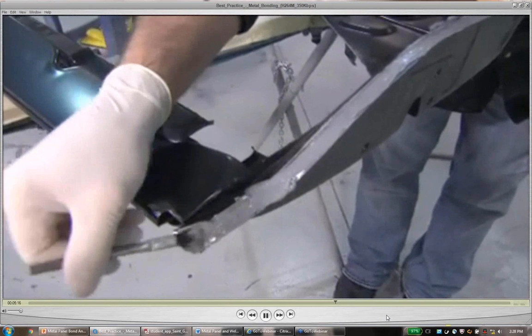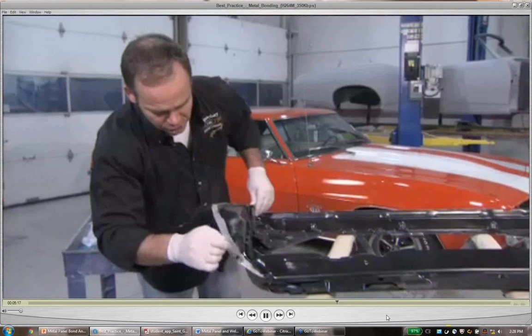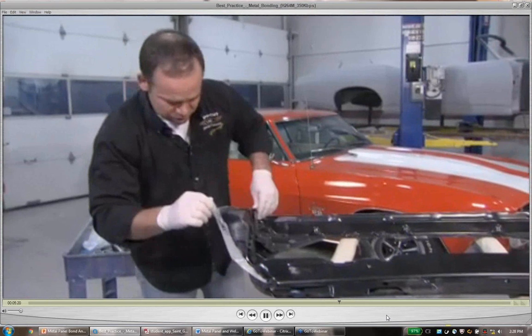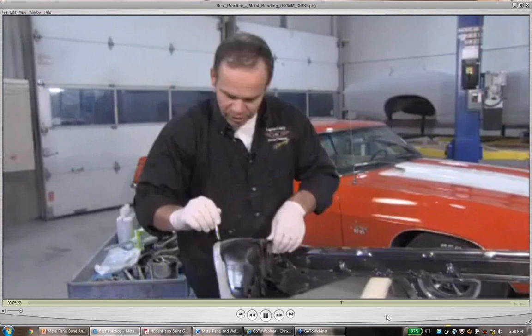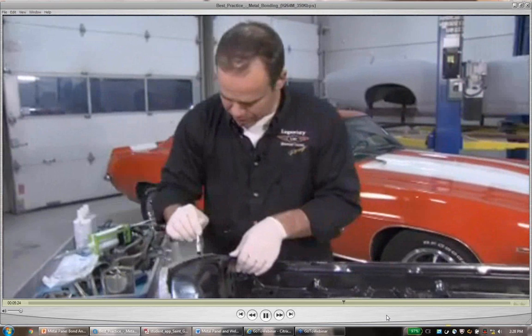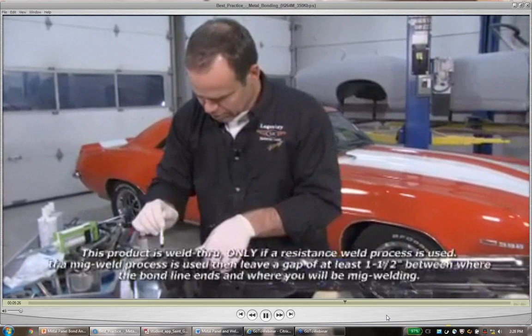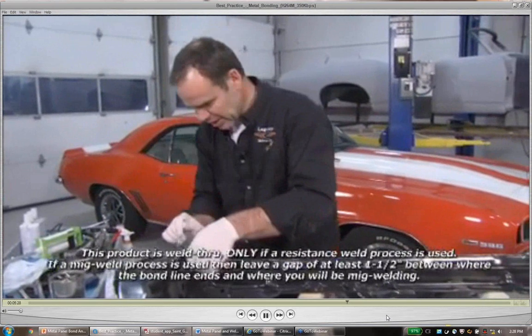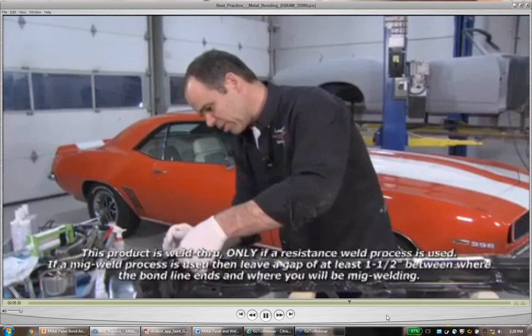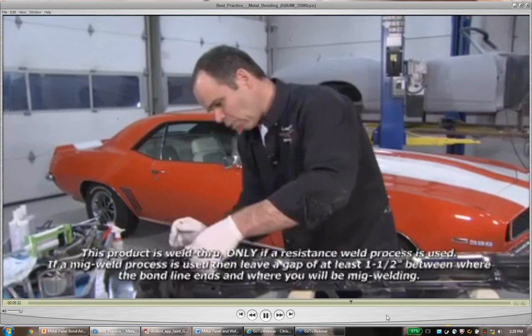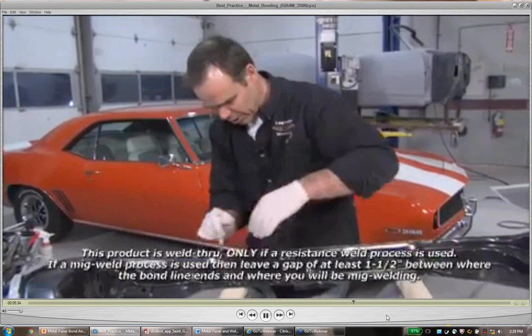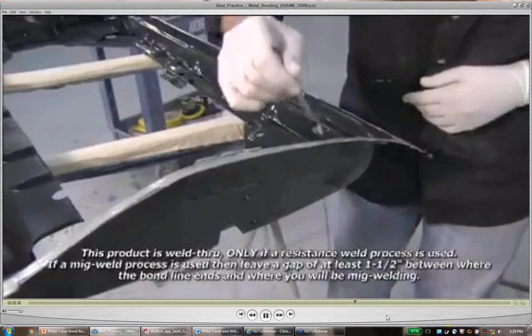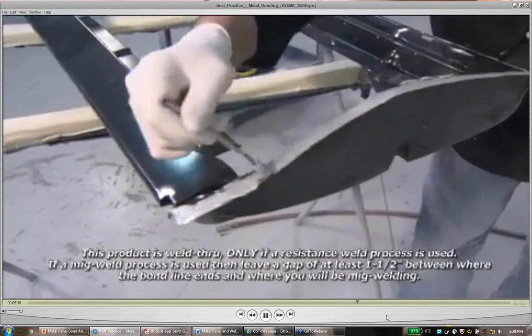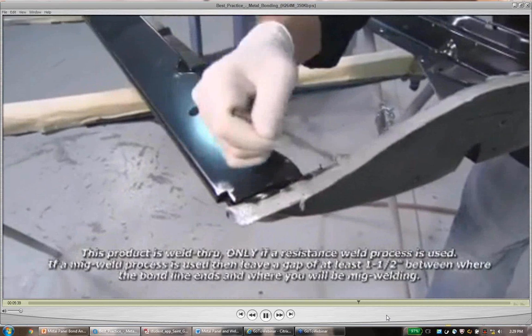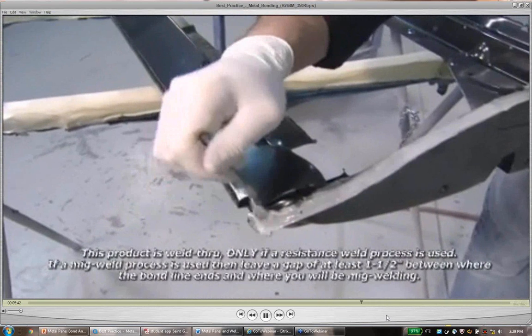Because this is a great corrosion-resistant product, you want to make sure that you cover all of the bare metal with the material. The other nice thing about this material is it's a weld-through material. So if you wanted to weld it as well, you're more than capable of doing it. The extra 10 seconds it takes to go over it twice is worth it, especially bonding aluminum and steel. You want to make sure it's covered nicely.